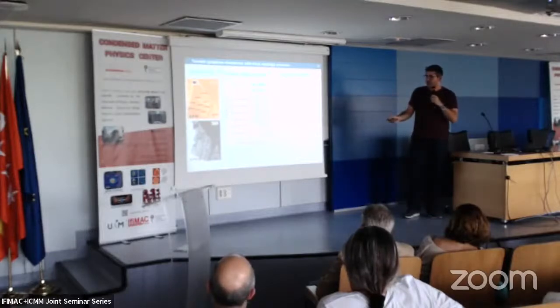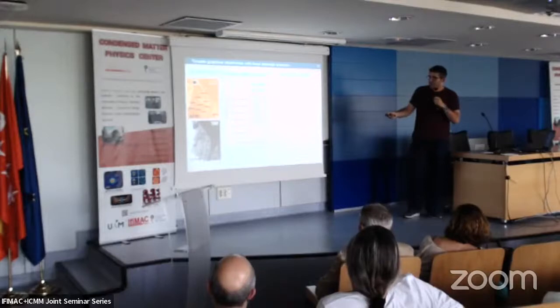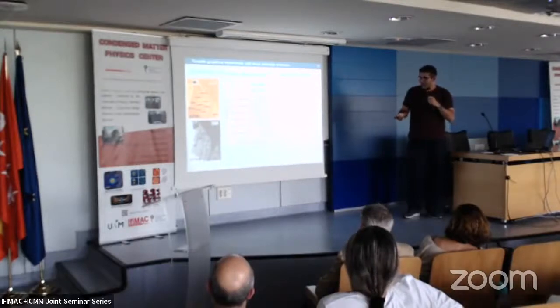So we can take even images, because it allows also mapping the areas. We can take images of the carbon split, how it's varying in a given area of our sample. So we can see that areas at higher pressures appear in a different color. So we can come now here with our beam and take individual spectra in each of the regions.